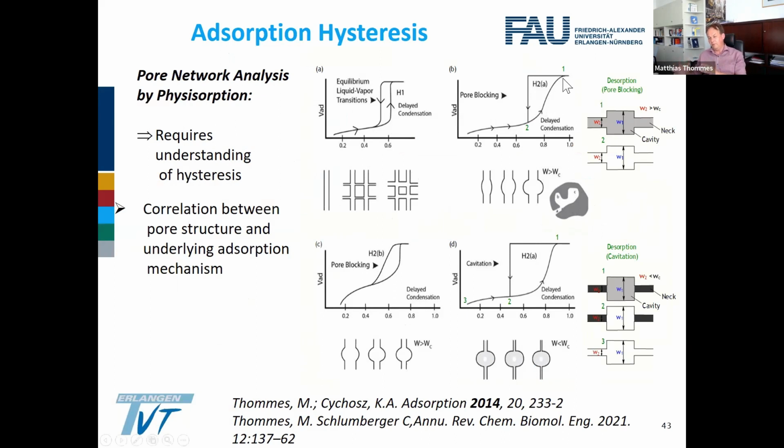And for doing this quantitatively correctly, we now need to apply a model, for instance, the mean field density functional theory model, which takes into account in a quantitative way this delay of condensation as well. From the desorption, when we analyze this, we will only get information about the characteristic entrance into the pore system. So everything empties when we empty the neck.